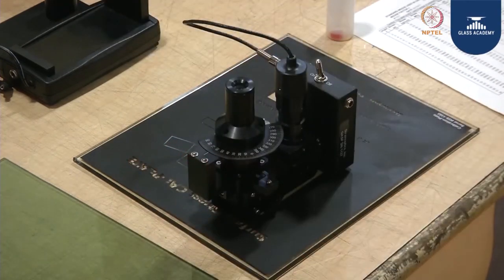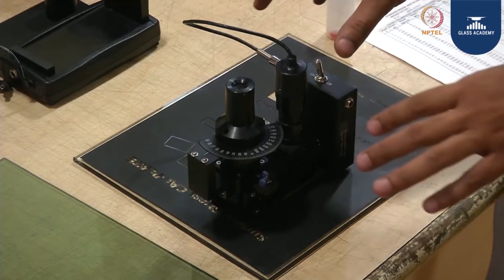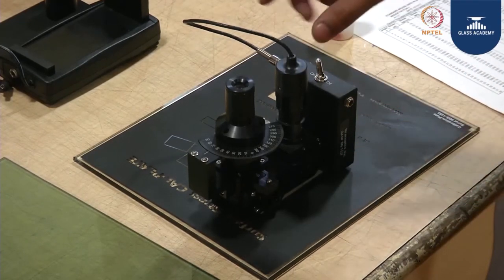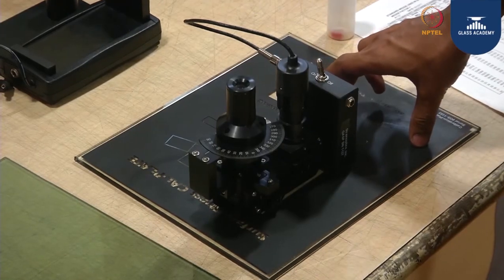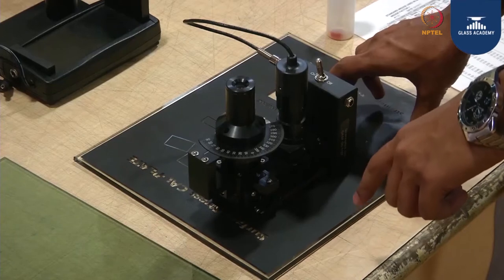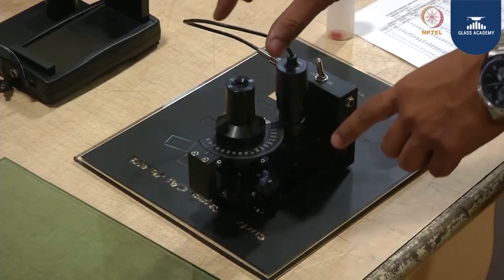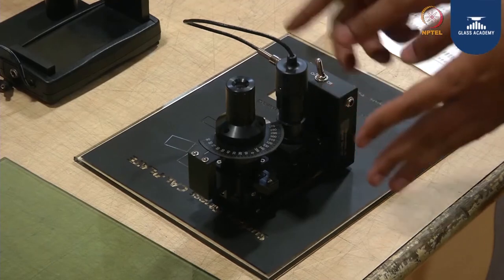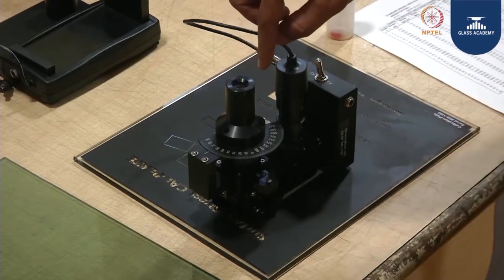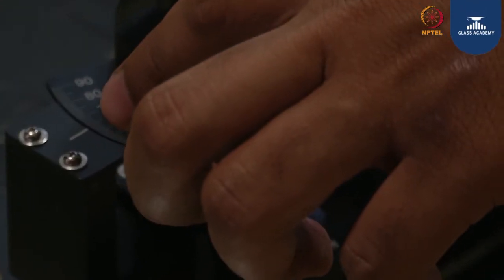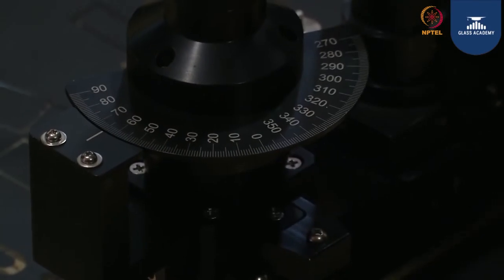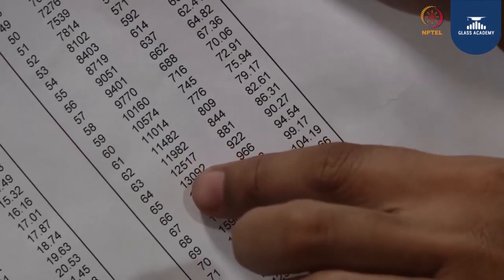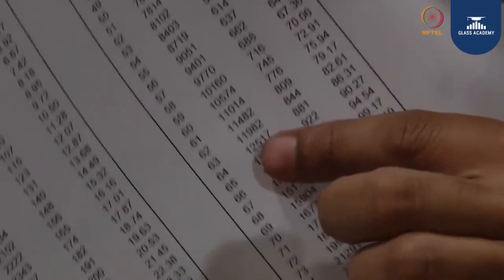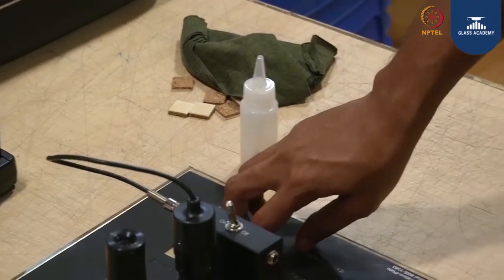Now we are doing self-calibration. When I see any toughened glass or any heat treated glass, I will be able to see the stress lines. Through this angle and width gauge, I am able to match the stress lines of both the equipment and the glass. If you zoom in on this particular area, the stress lines are colliding at an angle of 65 degrees. Now we need to cross verify. At 65 degrees, what is the stress level induced? It is 12517 as per the chart, and here it is coming 12520.